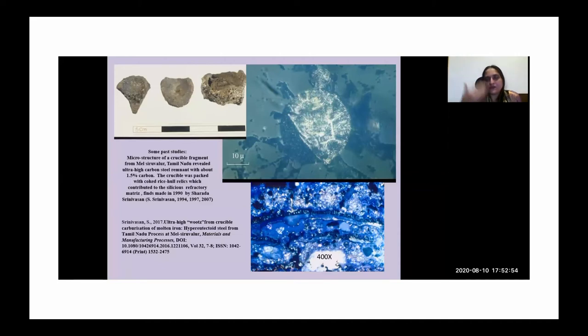And when you make a cross-section or metallurgical section of the crucible, because it's very vitrified, you can actually make a section just like a metallurgical section. And then you see that it has these globules, or prills, as you call them. And the globule is also quite perfectly spherical, as you can see. So what that indicates is that it has got carburized to really the molten state. And this molten carburization happens only if the temperature was quite high, and it would also have needed very highly reducing conditions in the furnace of at least 1200, if not 1300 degrees centigrade.